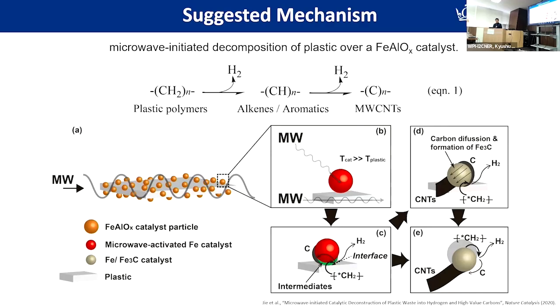We also did some mechanism study, and from the characterization, we understand there is a huge temperature gradient between the catalyst and the polymers. The carbon formed at the very beginning will react with the iron to form iron carbide, and then the carbon will grow from the iron carbide into very high purity carbon nanotubes. So we generate very high purity carbon nanotubes without observing, for example, other types of carbon material.